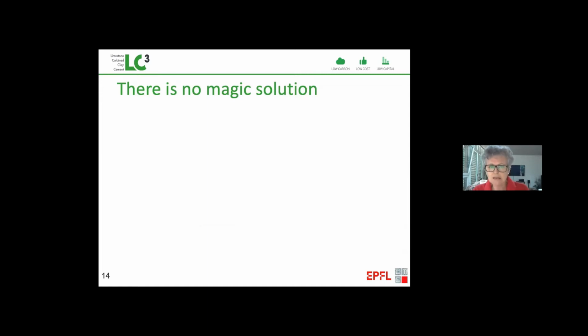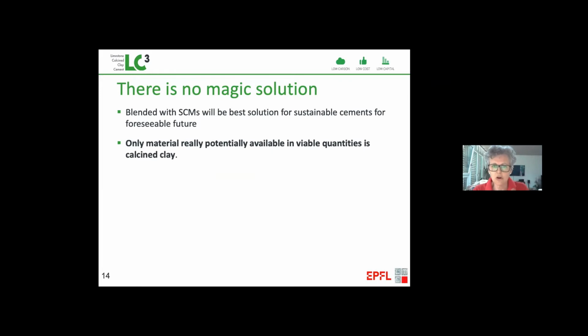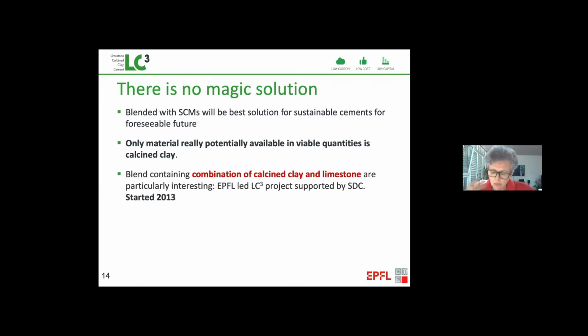So to summarize that, I think it's important to emphasize there are no magic solutions out there that we haven't discovered. The best solution, and really the only one that's going to give scalable reduction of CO2, is to increase levels of substitute material. The only material that can really extend that level of substitution is calcined clay. And what we really discovered at EPFL was that if we now put together this calcined clay with limestone, we can get particularly high levels of substitution.